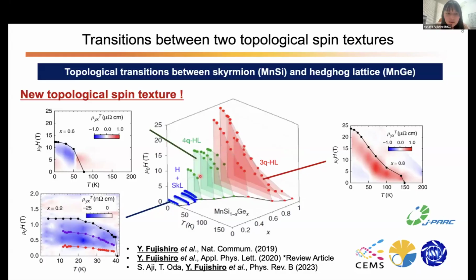But in the middle part of the region, we observe a rather unusual sign change of the topological Hall effect from positive to negative, and then again to positive near the transition temperature. So actually, the origin of this sign change is not revealed yet. But one thing we can say is that the spin configuration of these spin textures are different, which really affects the topological Hall effect in this material. So I would say that the transport measurement is again a very important proof for corroborating the presence of topological